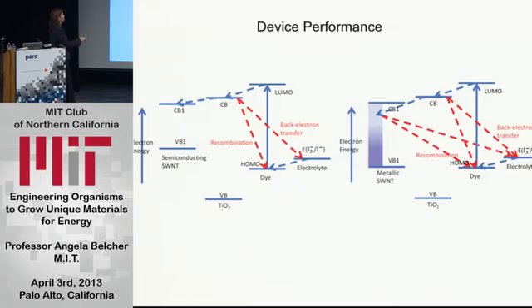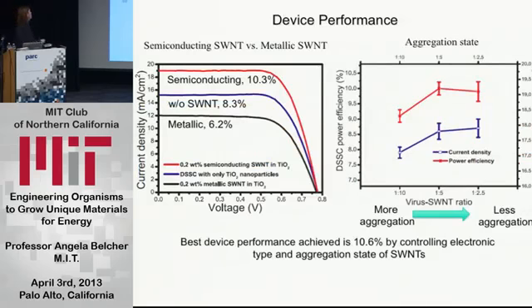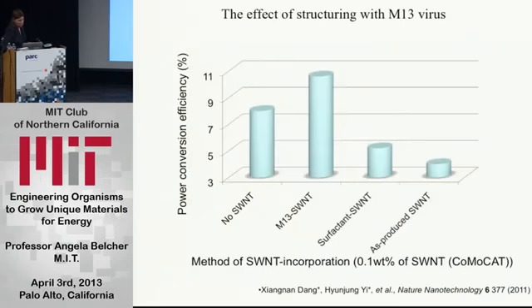Now, if you put metallic carbon nanotubes in, you actually have additional recombination, which leads to decreased efficiency. And so now you're looking at current density of devices here, and adding metallic carbon nanotubes is actually decreasing our efficiency. Without carbon nanotubes, at the time, the best dye-sensitized solar cells we could make were about 8.3%. But then adding our semiconducting ones with the virus, we increased it to 10.3%. And then playing around with the ratio of virus and aggregation, we were able to increase it finally to about 10.6%. And so what you see here is basically you get a 33% increase from adding 0.1% biology to the system. And that was another big deal for us because it showed that a little bit of biology could go a really long way.